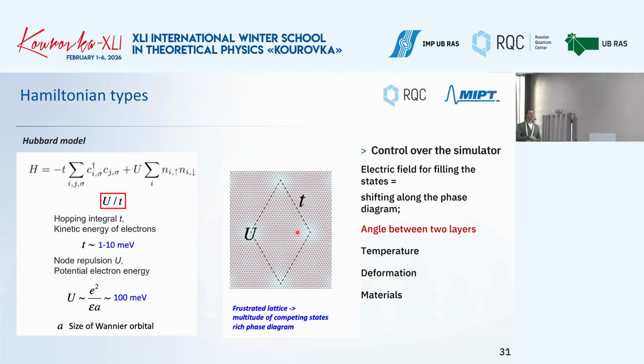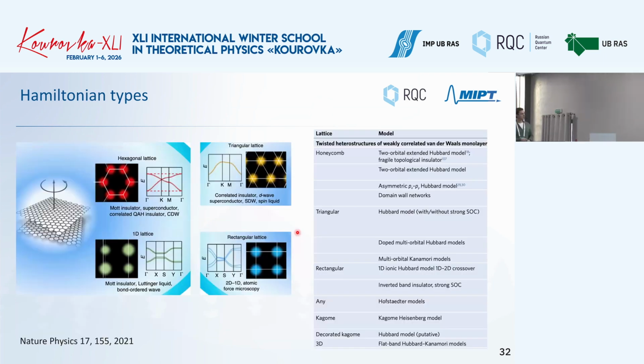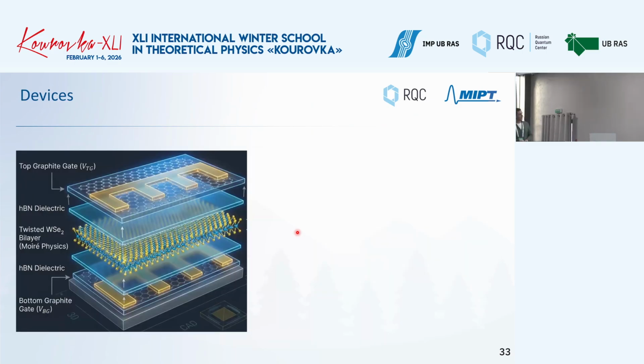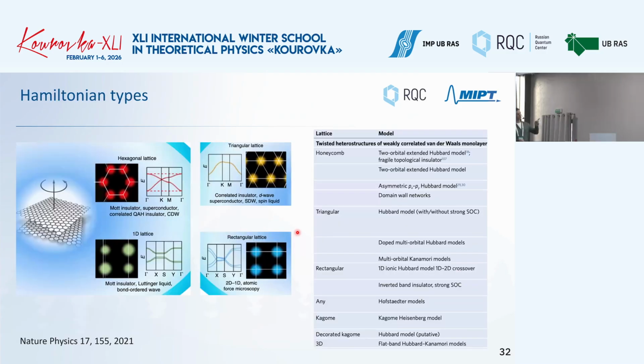which can be described by the Hubbard model. And you can control the simulator by applying an electric field or filling the states. You can change the angle between two layers, temperature, deformation, and materials, in order to control these two parameters. And already in 2021, it was demonstrated that different Hamiltonians, different lattices, and different models can be realized in these stacked 2D materials. You can see here.